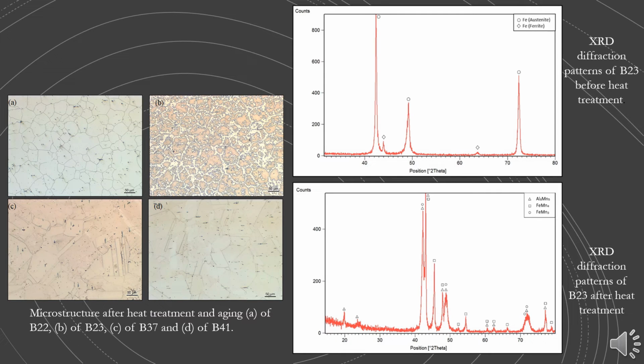The microstructural analysis of all the alloys after 8 hours of aging shows that B41 and B37 still have the typical austenitic structure as before the heat treatment, while B23 develops different phases and B22 still has the austenitic structure with more rounded grains. An XRD analysis of B23 before and after aging shows that after the heat treatment, B23 develops intermetallic phases, which explains the change in its microstructure and its brittle behavior during the tensile test.